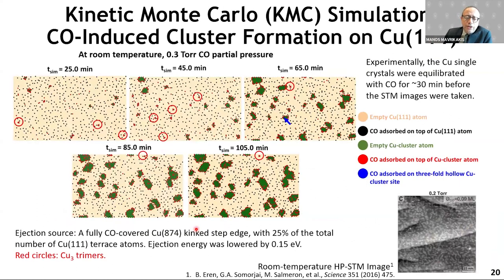Now, after you do this, you ask the question, how stable are these enormously active sites, the trimers? So we use kinetic Monte Carlo simulations, taking advantage of the energetics that we developed with density functional theory. We evolve over time the formation of various atoms and clusters to simulate the environment shown here in the experimental results.